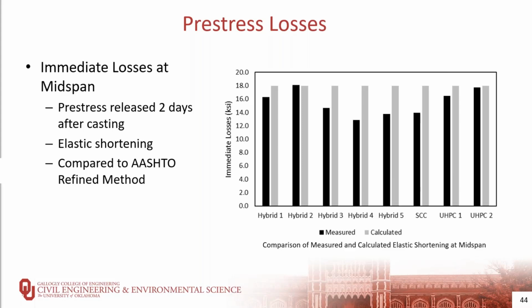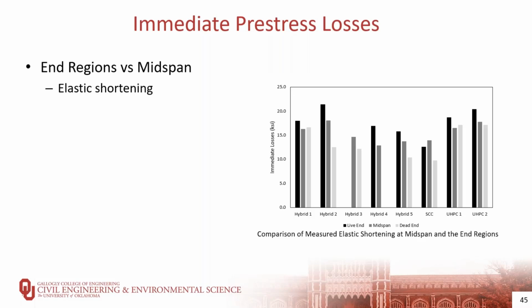Hybrid 3, 4, 5, and the SCC obtained similar immediate pre-stress losses, but in order to understand the behavior of the pre-stressing stress transfer along the girder, this graph would show the end regions and midspan elastic shortening for all the beams. All the hybrid beams followed the same trend. The UHPC end region and midspan had similar elastic shortening losses, whereas the SCC end region had a lower value.